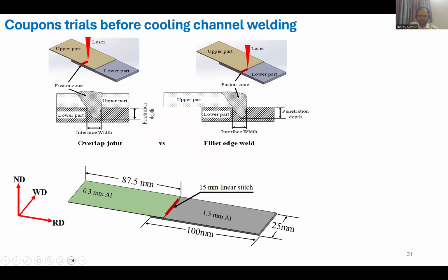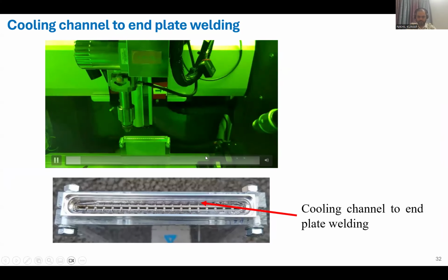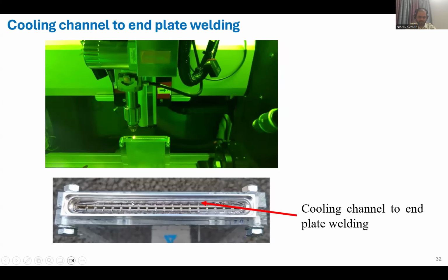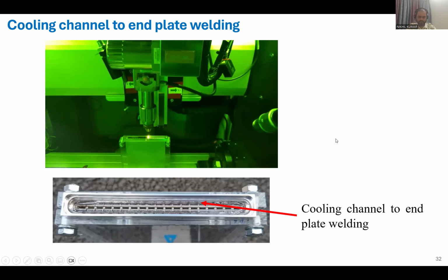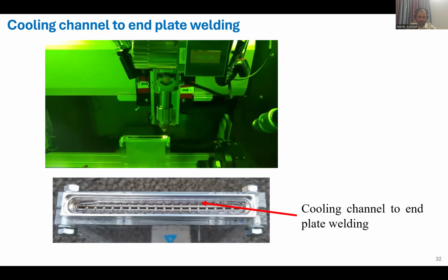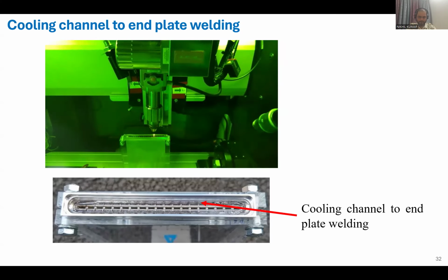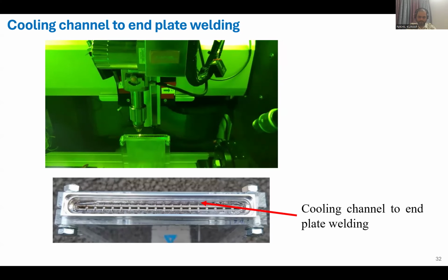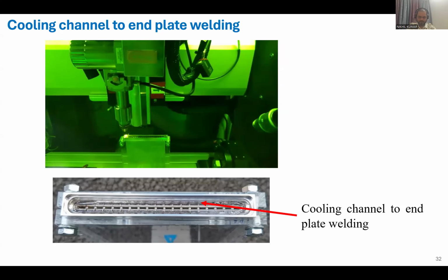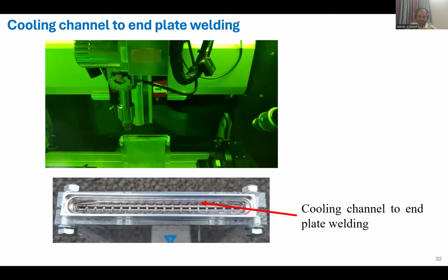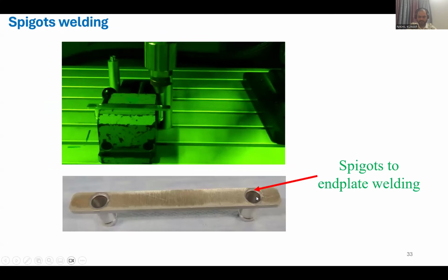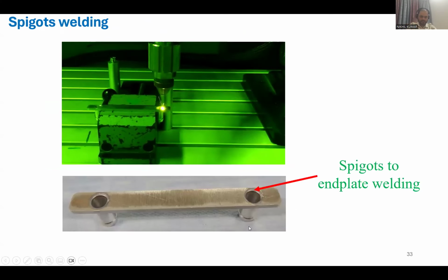I did some initial coupon-based trials. Once I was satisfied with the parameters, with no bottom sheet penetration, low pores or no pores, and no cracks, I implemented those parameters to connect the cooling channel to the module manifold. So this is welding. Yes, this is successfully welded. This is the final product after welding: the cooling channel to the module manifold weld, and this is the spigot, used for flowing the cooling liquid.